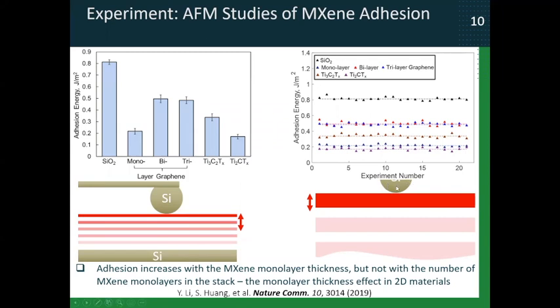a hypothesis that this effect, we call it the number of monolayers effect on adhesion force, depends significantly on the thickness of your monolayer and interlayer distance. So basically, adhesion interactions in the case of graphene propagate deeper than the topmost monolayer. Why? Because the monolayer is just an atomic layer thick, so it's very thin, and the interlayer distance between graphene monolayers is also very small compared to MXene, where even the thinnest MXene, titanium 2C in our experiment, already has 3 atomic layer thickness, and the interlayer distance between the flakes when you stack them is also much larger than in